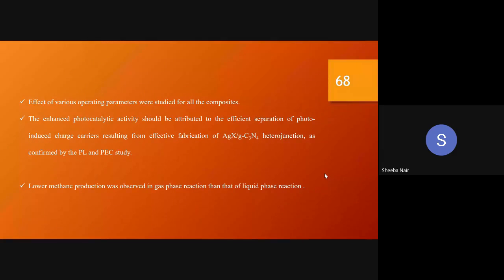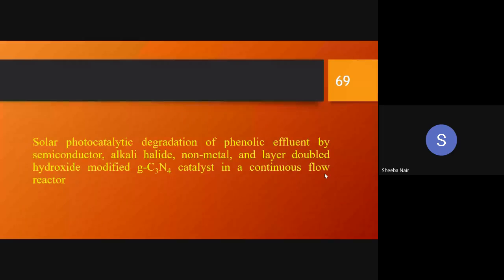And surprisingly, ethanol yield was observed in the silver iodide system, which is yet to be established. And the gas phase system gave us a low methane value than your liquid phase reaction. That was your energy application, CO2 conversion to useful fuel.